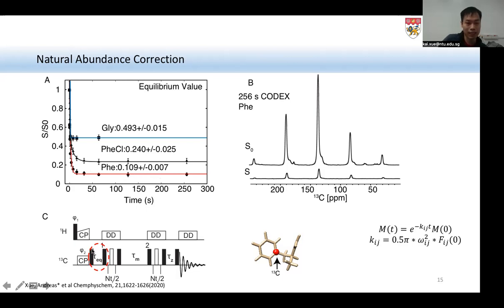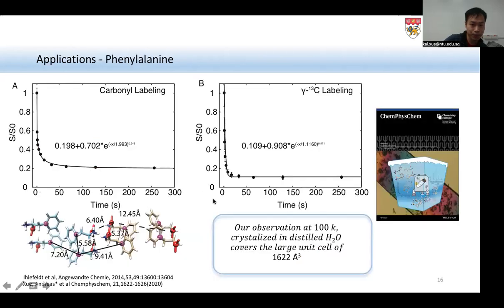So we propose a pre-equilibrium part before the encoding and decoding of CSA. After the CP and equilibrium, all the polarization is equally distributed on all the natural abundance spins, and then we can back calculate to compensate for this effect.